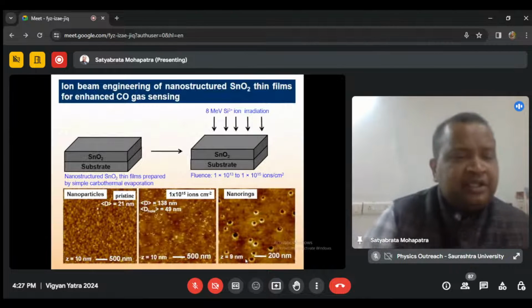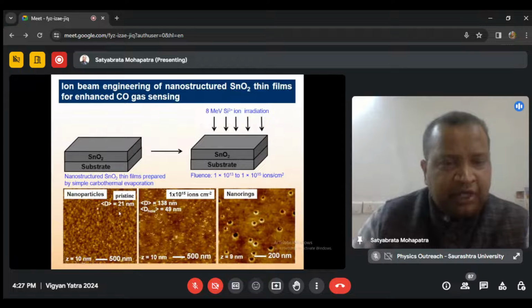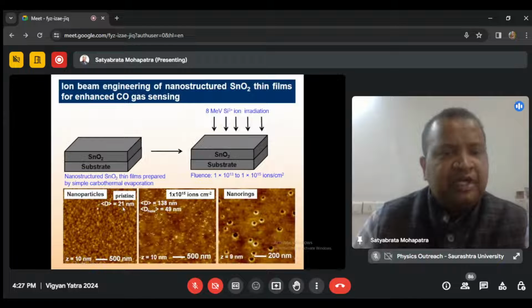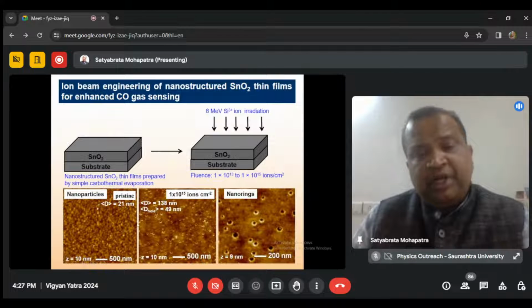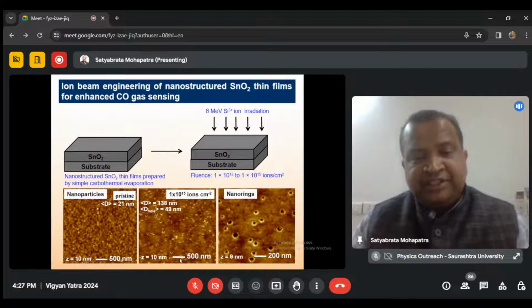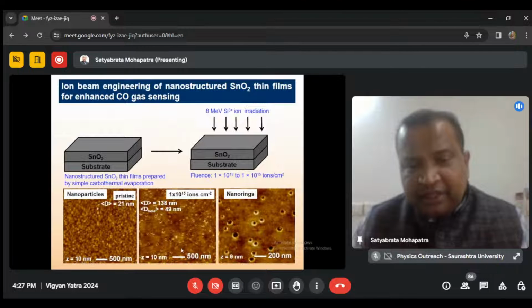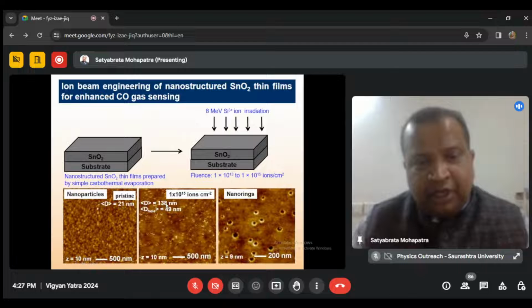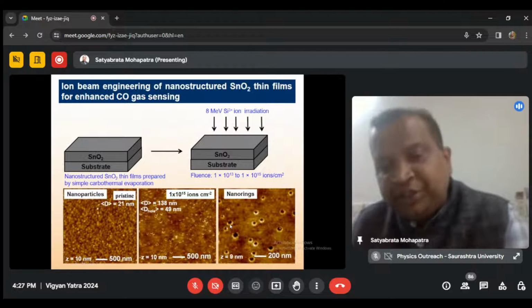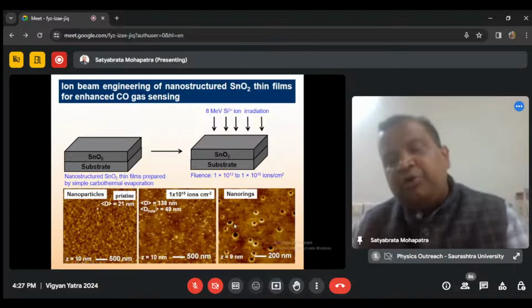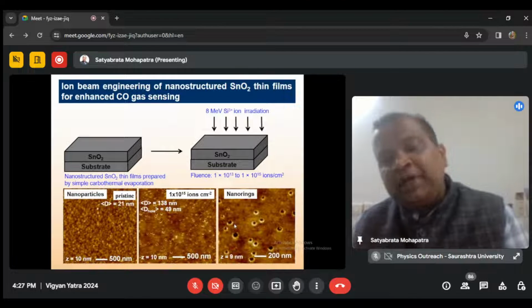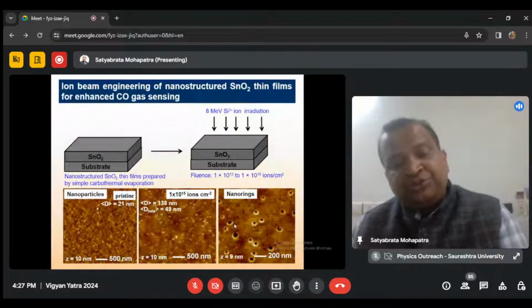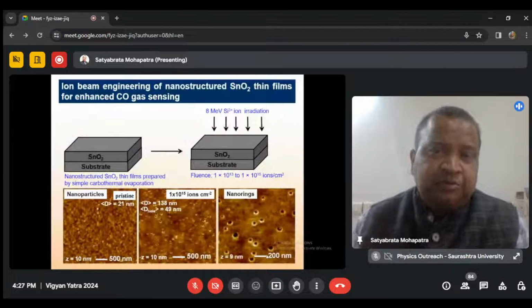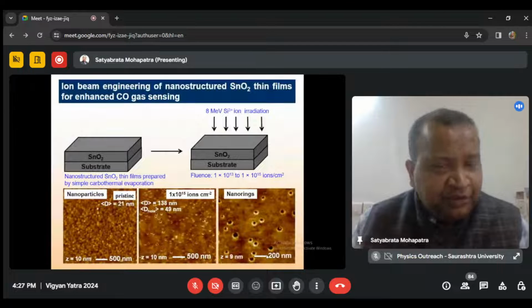Now you can see that the AFM results show nanoparticle film in the case of the pure tin oxide sample, with 21 nanometer average size. When you irradiate them with 8 MeV silicon 3+ ions, it develops nano rings. You can see nanostructures of average size 138 nanometer with a central hole. We call them nano rings because they are decorated by nanoparticles. So you have holes decorated very clearly by nanoparticles taking the shape of nano rings. So you can fabricate nano rings of tin oxide just by engineering a nanostructured tin oxide film.